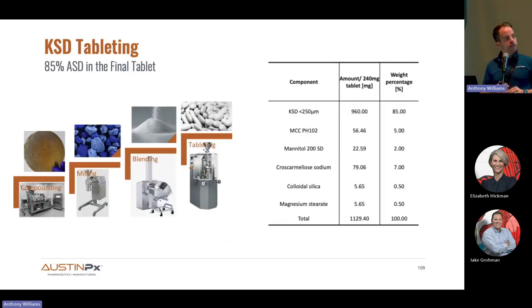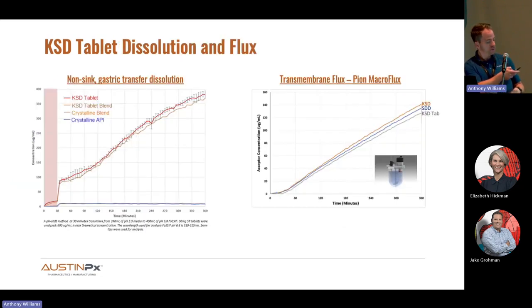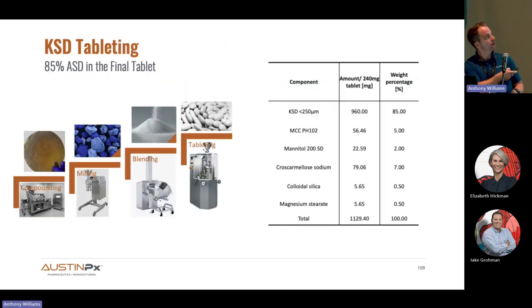So we took this optimized ASD intermediate and took it through our standard tablet manufacturing process, where out of the compounder comes our larger cookie. So you've got on your tables there an example of the discharge from the formulator. So this is what they look like, the same on the manufacturing scale with a larger diameter. And you take those through a milling process, and most of the time it doesn't make blue granules, but in this case they were blue. Then you blend them with external excipients and run them through your tablet press to arrive at your tablets.